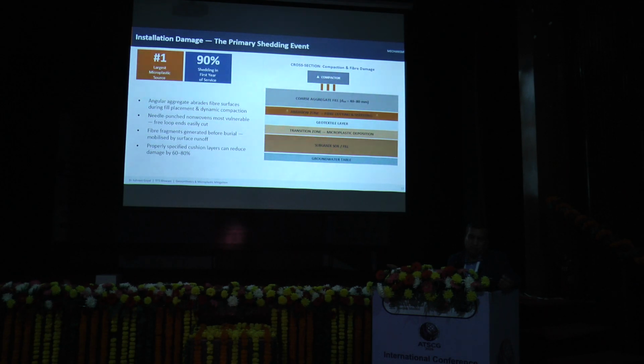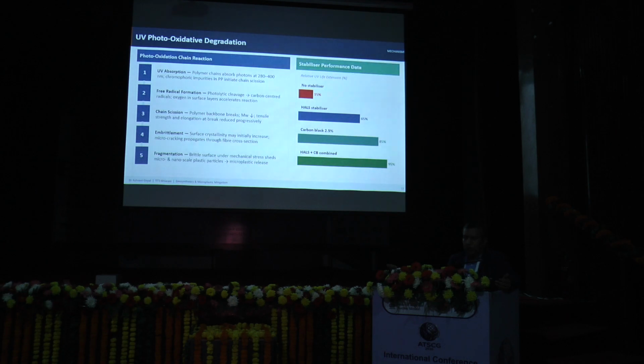If the bigger stone particles make direct contact with the geotextile material, there are greater chances of microplastic generation. UV photo-oxidation, if you see the image for the PP materials, is the most dangerous part, because due to the UV rays the degradation happens. To avoid the UV degradation of the geotextile material, we can enhance it with certain chemicals. In the comparative chart shown, if no stabilizer is added, only 15% of the life you can consider.